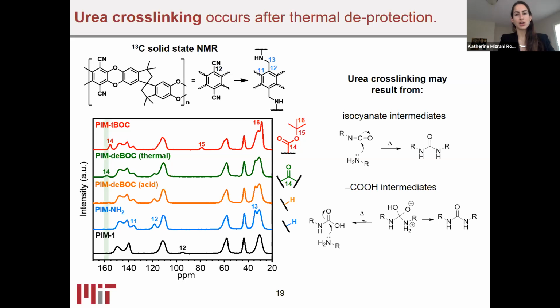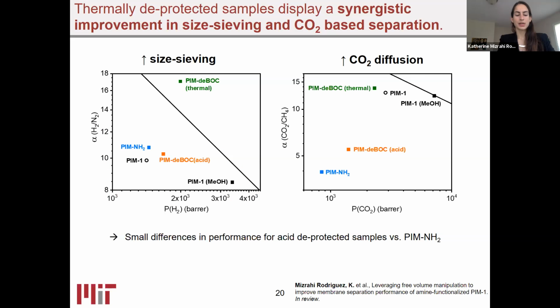So of course, having known this and having synthesized all of these materials, we were really curious to see what the performance looked like. Here you can see that we were able to characterize all of the samples in terms of pure gas permeation. For the acid deprotected samples compared to the amine functionalized samples, there's no primary difference. There's a slight increase in permeability, and this can be associated with swelling of the material in the presence of solvent for the deprotection process. And there are very slight changes in selectivity.